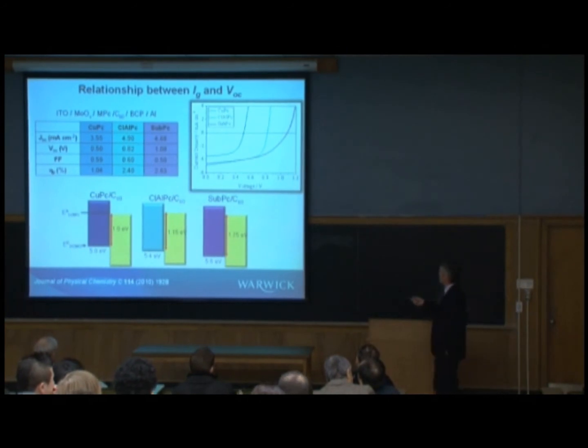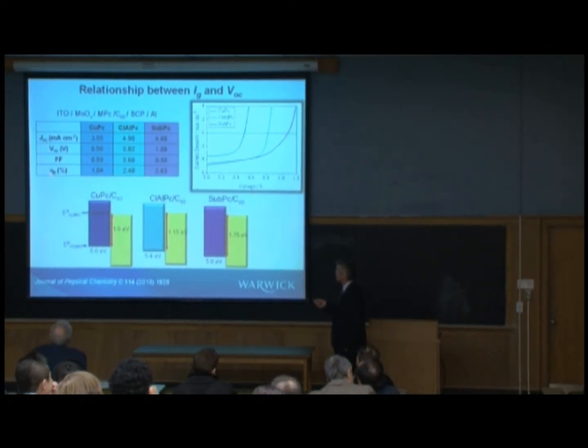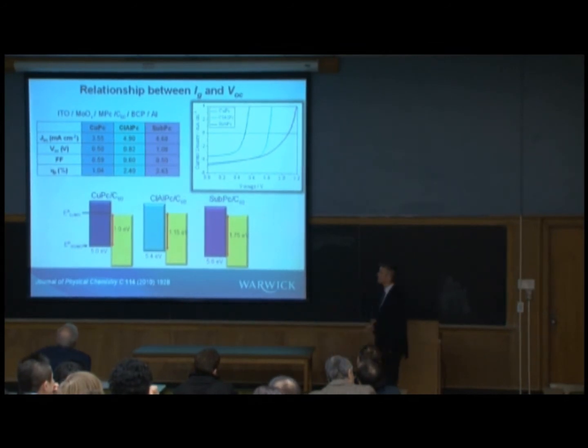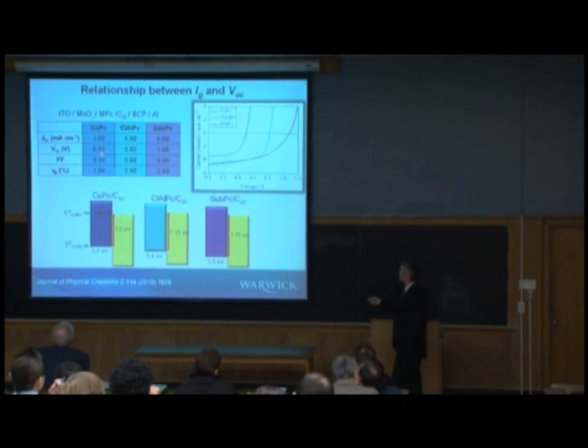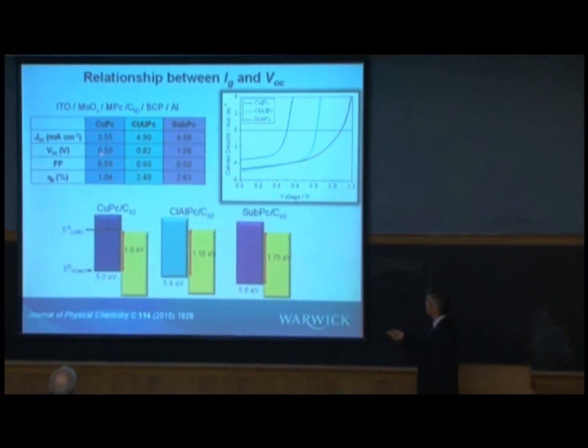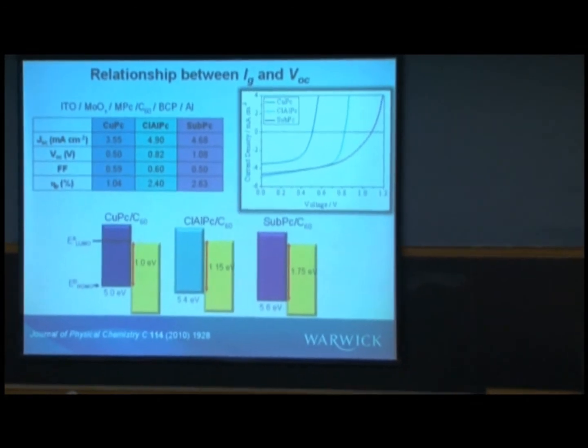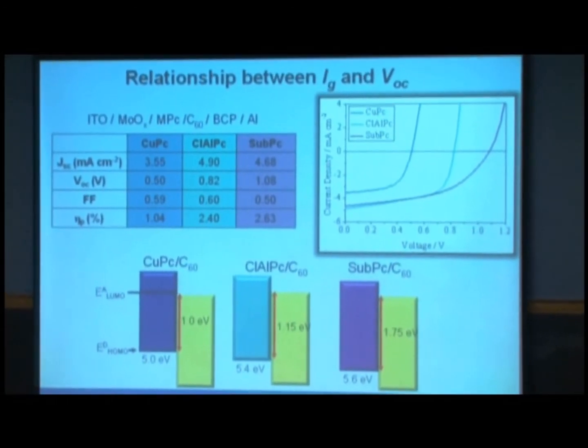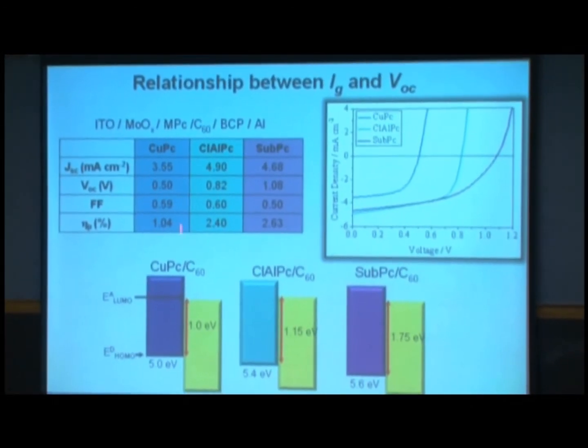The current voltage characteristics, this is a summary of the data, the current, the voltage, the fill factor, the efficiency, those 4 characteristics I talked about earlier. So voltage I just want to focus on. You can see it goes from 0.5 up to 1.08 for subphthalocyanine. In other words, as we increase the interface gap energy, we're increasing the voltage as you'd expect. So that's just proof that it does work, although there are quite significant losses.